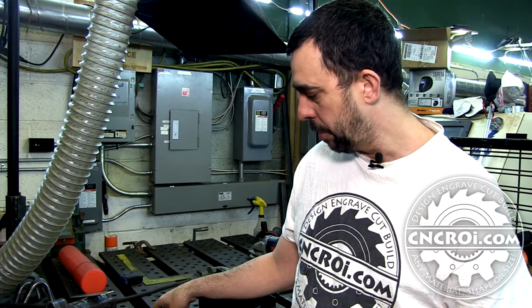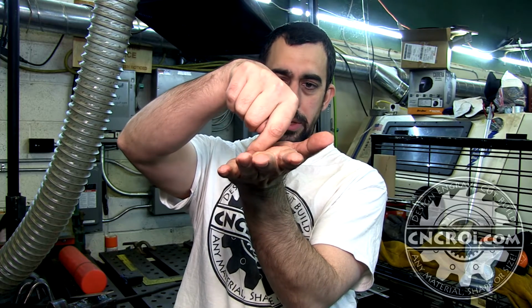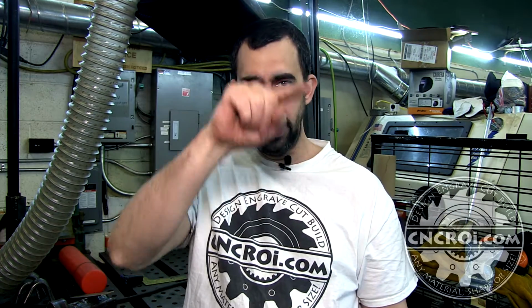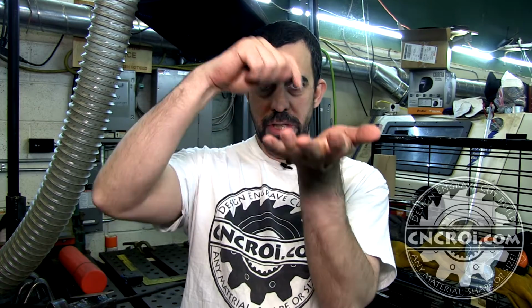Now in our college, whenever we do tests, because you know you do a lot of welding, then you look at how to break your weld and see what the results are. If you want to know if you have really good penetration in your weld, basically just make a T-joint and weld all the way down, and then you break it the other way. And if you see it like a saw, that means you have awesome penetration. If you just see a clean break, that means you basically had no penetration. So although the weld looks really, really nice, it's absolute crap.